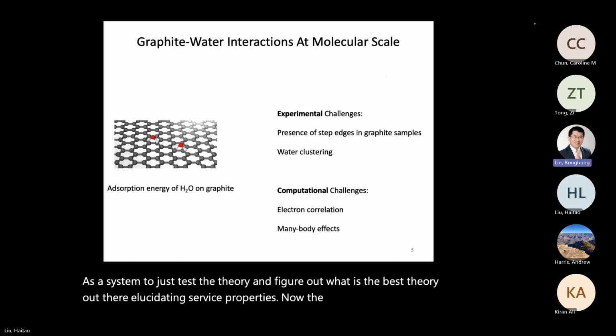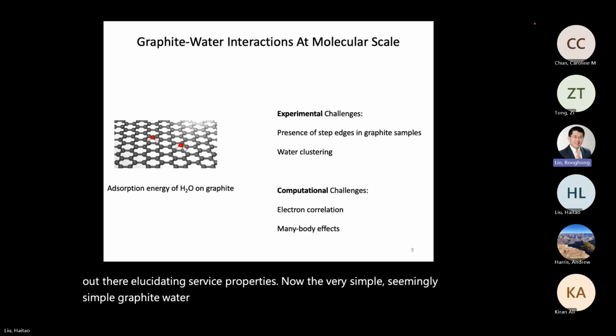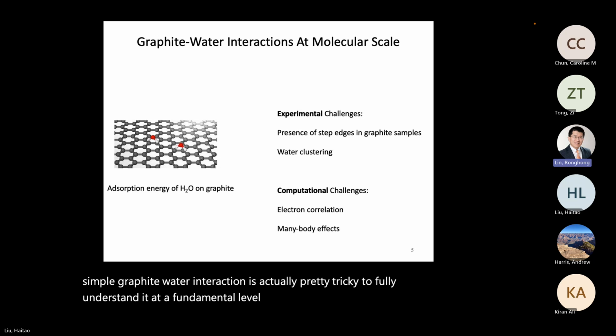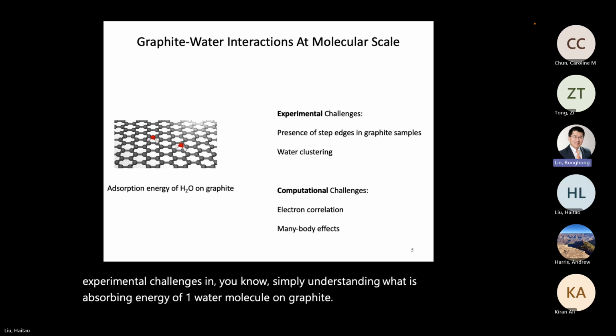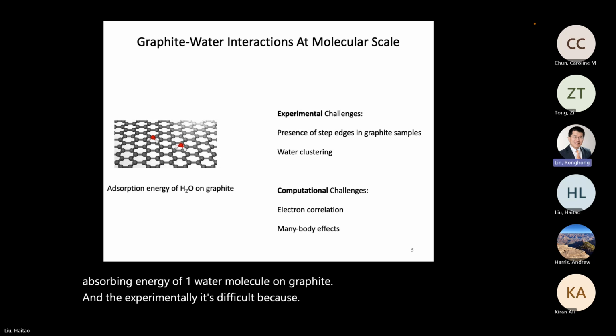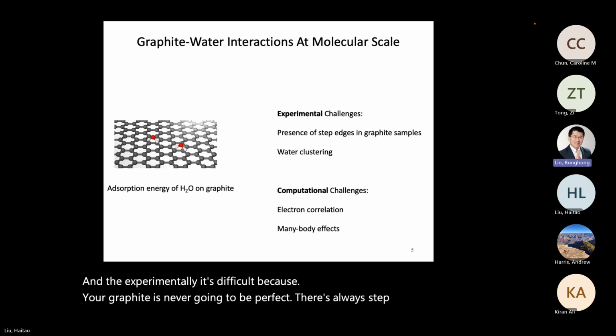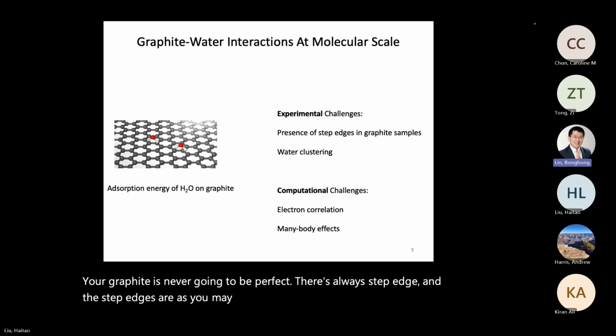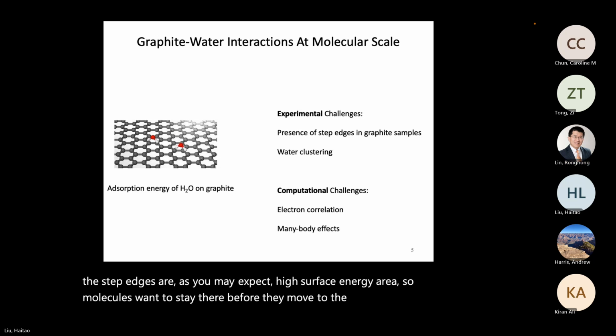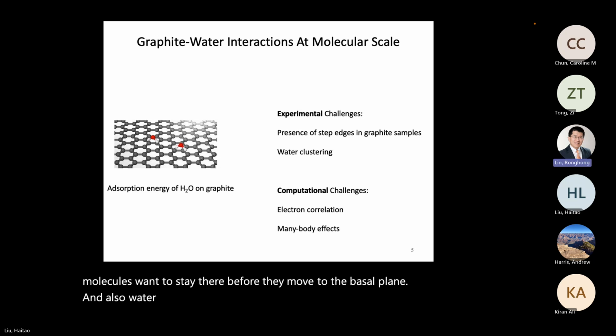Now, the seemingly simple graphite-water interaction is actually pretty tricky to fully understand at a fundamental level. And there are a couple of experimental challenges in simply understanding what is the absorption energy of one water molecule on graphite. Experimentally, it's difficult because your graphite is never going to be perfect. There's always step edge. And the step edges are, as you may expect, high surface energy area. So molecules want to stay there before they move to the basal plane. And also water likes to hydrogen bond to each other. So it's just difficult to get this isolated water molecule on graphitic surface.